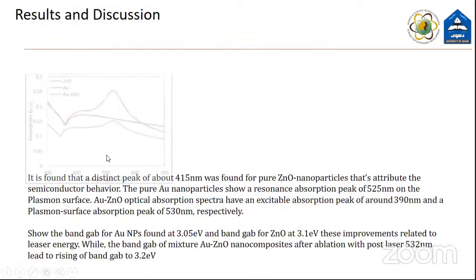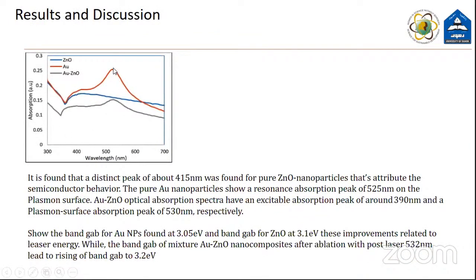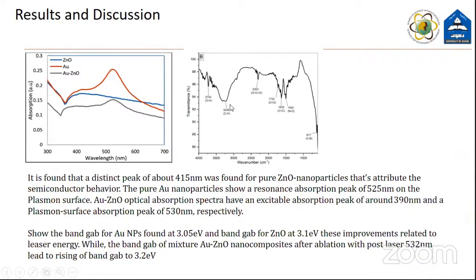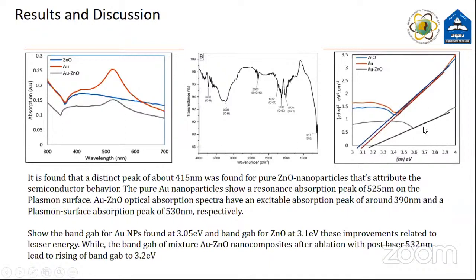So, as you can see, this is the absorption for Au nanoparticles and ZnO nanoparticles, and this line shows the mixing of Au and ZnO nanocomposites. The absorption decreased to 0.15 when mixing and when irradiated by the pulsed laser. This diagram also shows the FTIR, with all the ligands and peaks showing the interaction or adhesion between ZnO and Au. Also, this shows the band gap for ZnO, Au, and Au-ZnO.